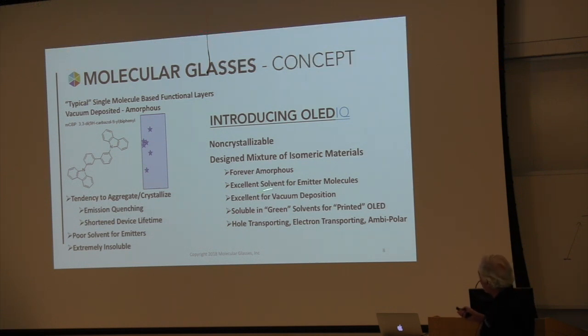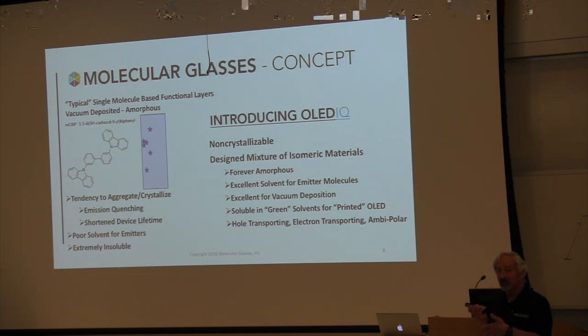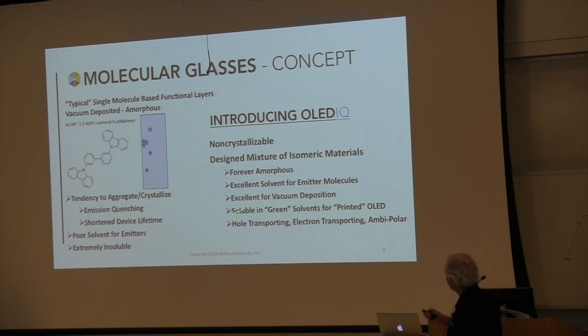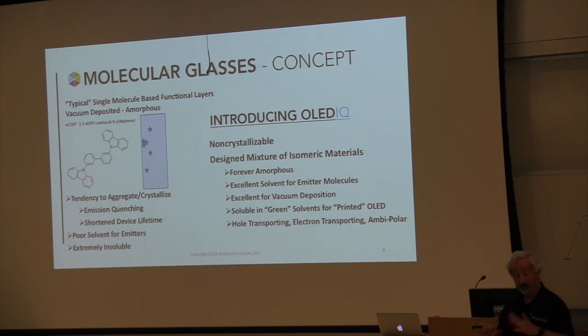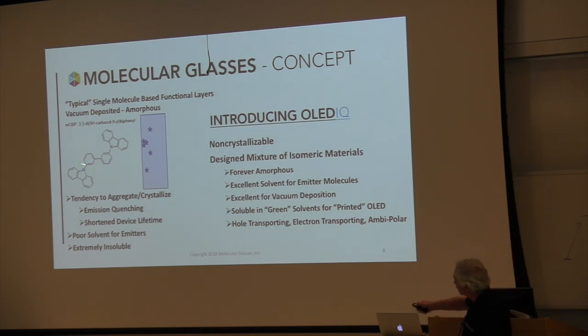Actually, they vacuum deposit very nicely because they melt readily. It's a mixture and very uniform vacuum deposition. So in fact, these are very suitable for vacuum depositing, so they can be drop-in replacements for the materials that are currently being used. They're soluble in green solvents. They're very soluble. You can make inks out of these, and we have made inks, and you can actually print them. We can make them hole transporting, electron transporting, or ambipolar, meaning both hole and electron transporting. And we do that by changing the functionalities on these molecules.